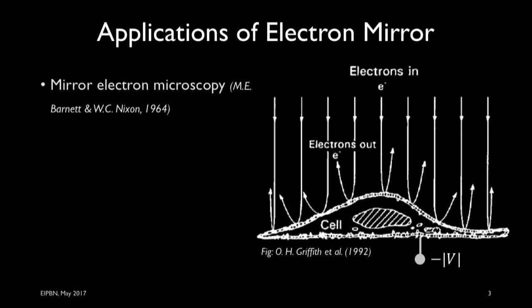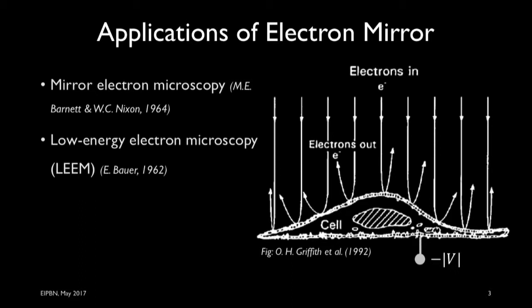So let's go over some of the well-established applications of electron mirrors, two of which are mirror electron microscopy and low-energy electron microscopy. In both cases, the sample is held at a negative bias on the surface of an electron mirror. In mirror electron microscopy, the bias is large enough that the electron would never directly interact with the sample. It slows down somewhere above the surface of the sample, and it gets reflected above the sample. In low-energy electron microscopy, or LEEM, the bias is not quite as large, but still enough to slow down the electron significantly, so that the electron basically gently lands on the top surface of the sample, and then backscatters, and those backscattered electrons are collected and imaged.